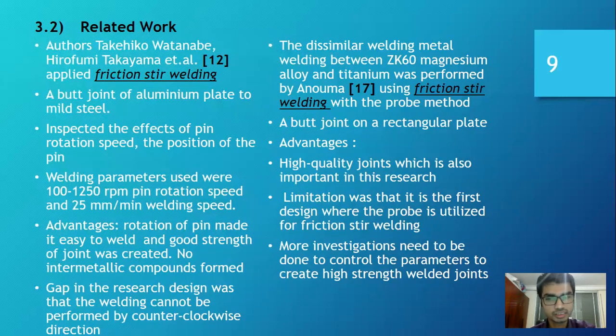In one of the other research journals, Anouma welded magnesium alloy and titanium using the friction stir welding method with the probe method. And here he has also created a butt joint on a rectangular plate. The advantage of this design was that high quality joints were created, but the limitation of this design is that it is the first design where the probe is utilized for friction stir welding. Hence, it's very difficult to control the parameters of this design to get a high strength welded joint.